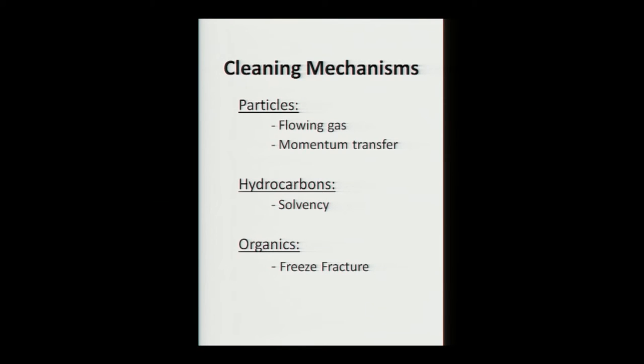Generally, when you blow nitrogen or compressed air on a surface, you get a flowing gas, what's called the aerodynamic drag force. That works down to particles in the micron range, thousandths of an inch, barely visible sized particles. What the CO2 snow does, it introduces momentum transfer, like playing pool. You're literally striking the particle on the surface and knocking it off the surface. And this works on what's called weakly bound particles. So that's the particle removal mechanism.